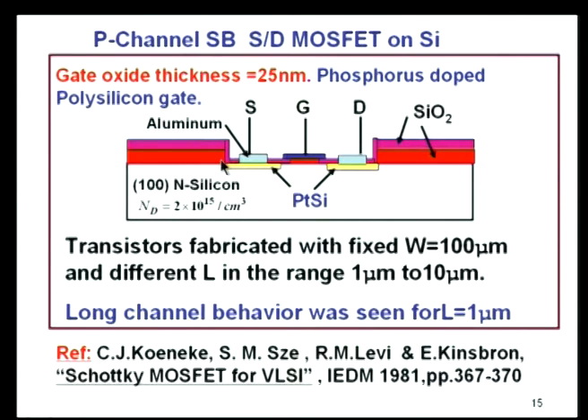Now, let me quickly go through some of the things that are there, like the P channel. The first of those, way back, was done by Sze and Koeneke: platinum silicide, a metal semiconductor contact at the source. You can easily make an ohmic contact onto P type material, if it is a P channel transistor. Platinum silicide can make ohmic contact onto that. That is a low barrier height for holes. So people thought of making a P channel Schottky barrier source drain MOSFET on silicon.